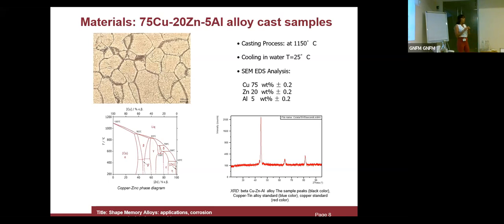It was really important for us to try to simplify our research and to have a beta phase brass. The beta brass is the phase that guarantees the shape memory aspect. So here we have the copper zinc phase diagram, according to which we selected the opportune composition, and then we analyzed the surface of our samples with an XRD instrument.